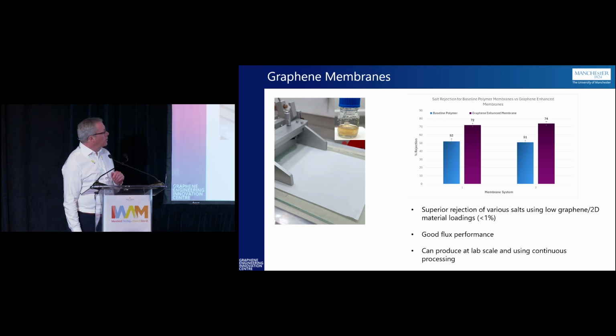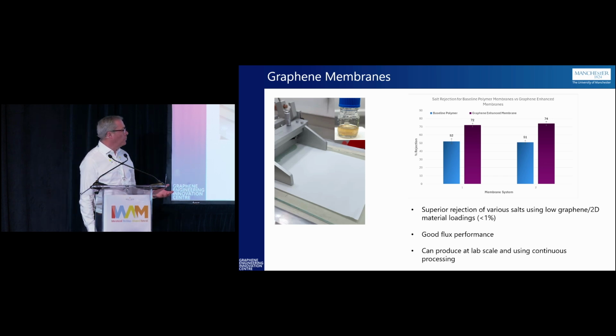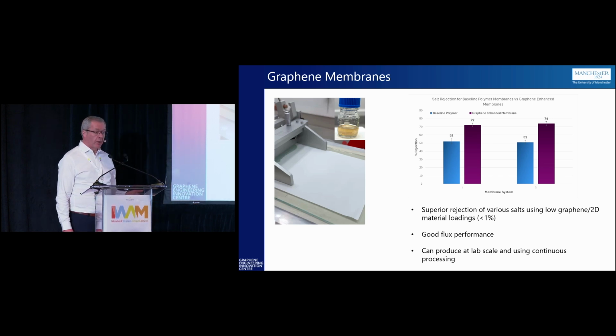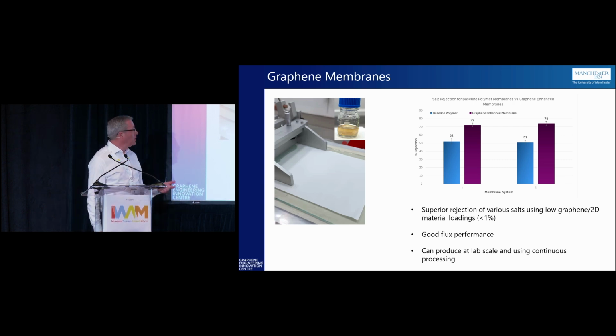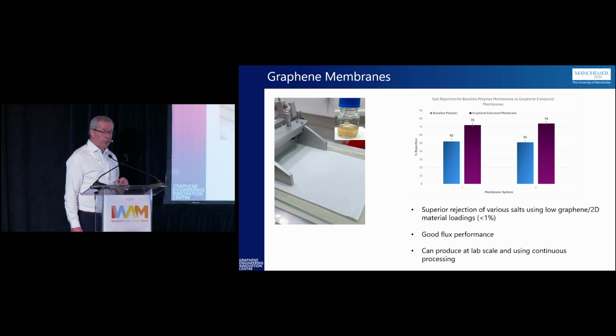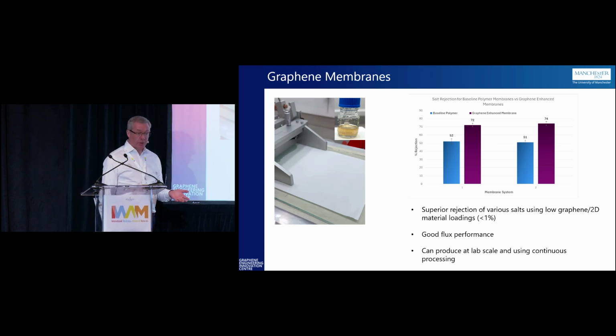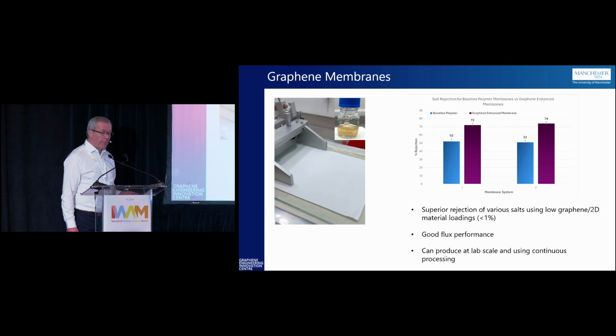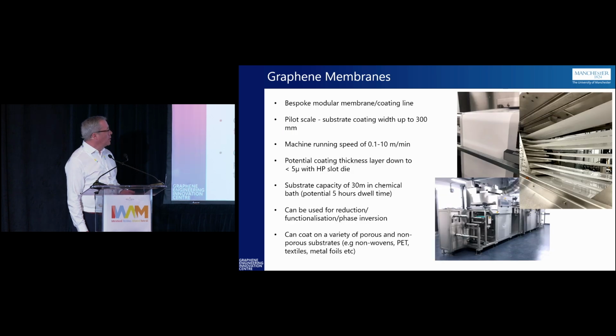As one example, this was on a spiral wound system. We've taken a standard membrane. So if you look at the base polymer, we wanted to do various designs of the base polymer. But how do we then take a base polymer with a known rejection rate and then populate it with nanomaterials? How do we improve that rejection rate? So you've got the theoretical from the papers. We then work on a 1 meter squared, replicating their formulation. So we've taken their nanocomposite or their graphene dispersion. We've populated it onto the base membrane. But then how do we take that base membrane with an uplift into commercial applications?